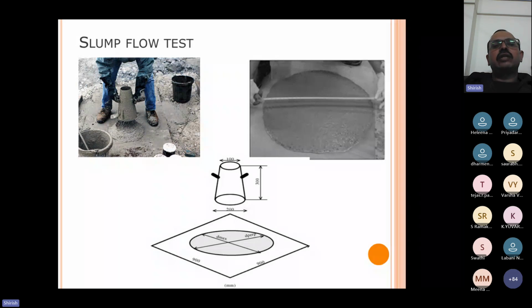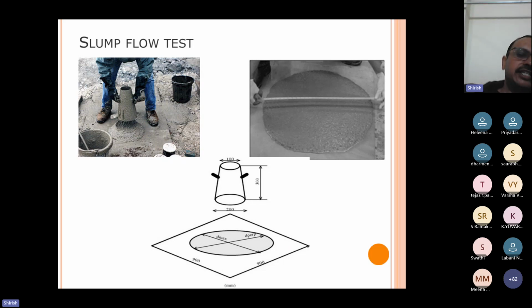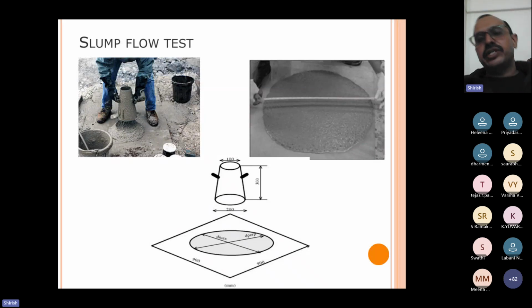Now here you can see in the left photograph, after lifting the slump cone, the concrete has segregated, or it is at the center only. So this is not a very good self-compacting concrete. On the other hand, on the right hand side, you will see the thickness of concrete is similar throughout. There is no segregation observed. No segregation observed means there is no location where the concrete depth is more because of a higher quantity of coarse aggregate. So on the right side, there is a very good concrete.